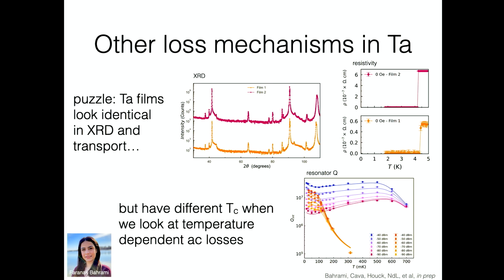Okay, so we've done an extremely deep dive in tantalum. And we had this kind of longstanding puzzle in the group, which was that we could deposit films that looked identical when we did DC transport and we looked at X-ray diffraction to characterize their crystallinity. But then when we did this power and temperature dependent loss measurement at microwave frequencies, they had very different behavior. And in particular, these films look like they have this exponentially temperature-dependent loss that turns on at extremely low temperatures. And we couldn't really figure out what was going on.